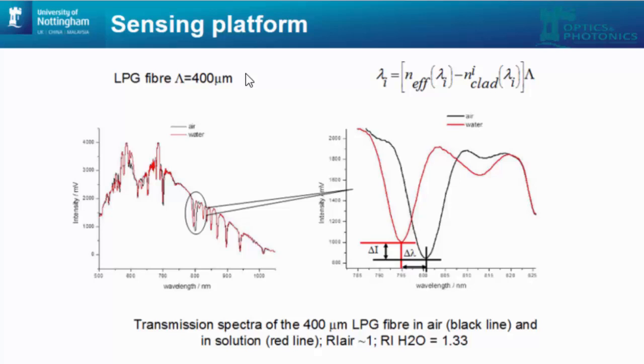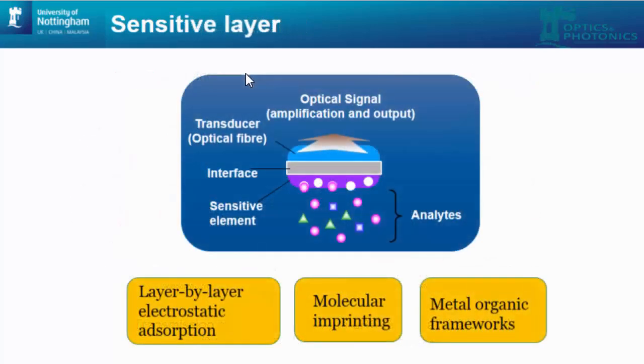The principle of operation, in essence, is similar to surface plasmon resonance, where you have a shift in resonance wavelength. To make them selectively sensitive, what we're doing in our work is functionalizing optical fibers with a sensitive material that will change its optical properties in response to the presence of the analyte we want to detect. So we use its selectivity. The target we want to detect will interact with this material, change its optical properties, and we probe these optical properties using the optical fiber.